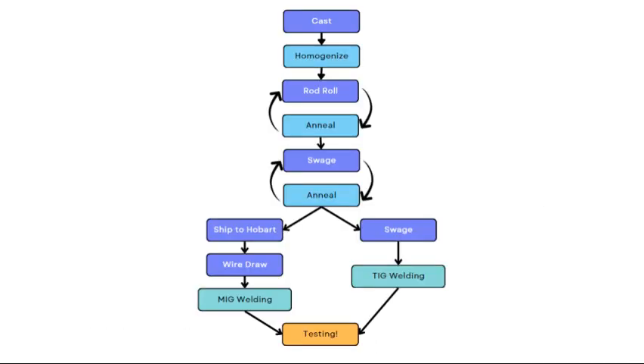Before any testing could happen, we first had to make our wire. This process started with casting and homogenization. Once homogenized, the bars were rod rolled and annealed as needed, and then swaged and annealed as needed. From there, most of the samples were sent to our sponsor for wire drawing, MIG welding, and testing, while a few of our samples were kept at MTU for further swaging, TIG welding, and testing.